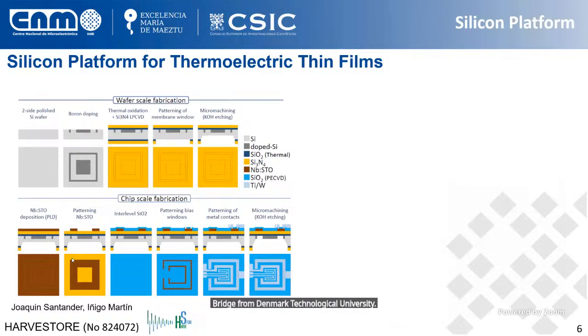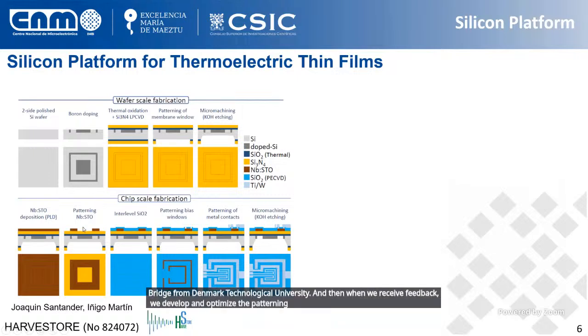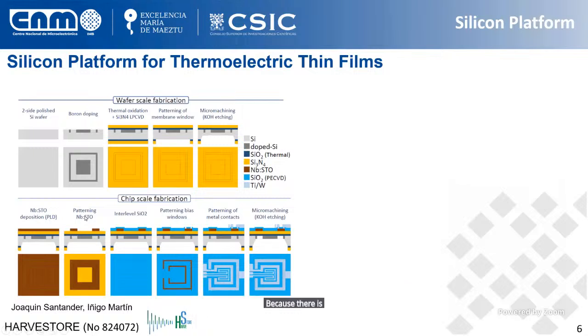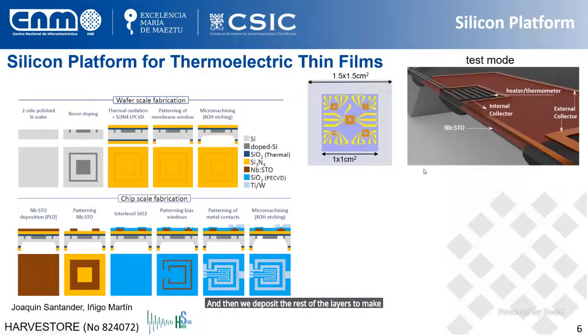And then when we receive it back, we develop and optimize the patterning by dry etching with physical bombardment, using argon ions in order to etch them, because there is no chemistry available for etching this type of materials. And then we deposit the rest of the layers to make these functional membranes.